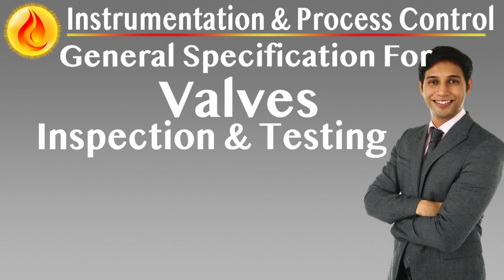Valves for service in oxygen, chlorine, hydrogen, or cryogenic applications must meet additional cleaning and testing requirements. Cleaning for oxygen service shall comply with ASTM G93 or equivalent and include a validated cleaning process, cleanliness verification, e.g. swipe test, UV test, and complete documentation of handling and packaging. Valves for cryogenic use must undergo cold performance testing at defined temperatures and verify seat leak integrity after thermal cycling.